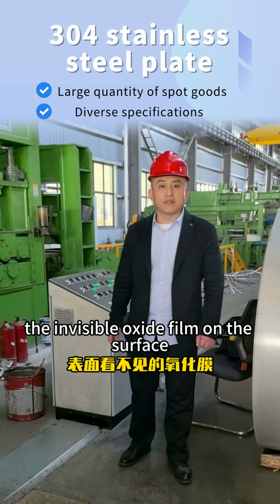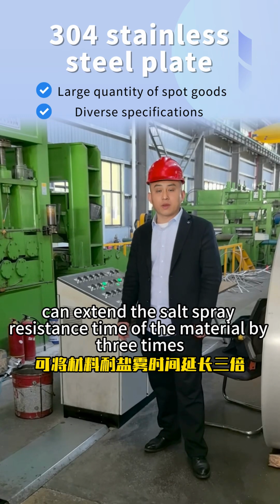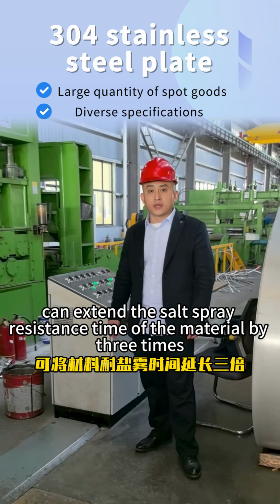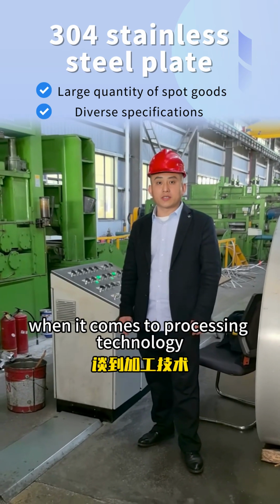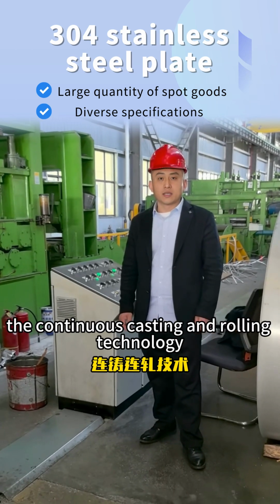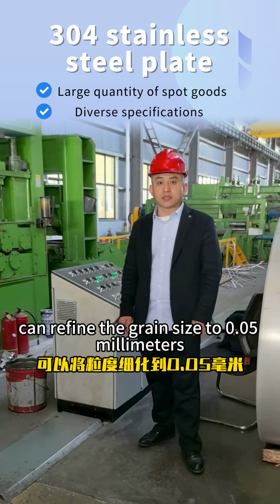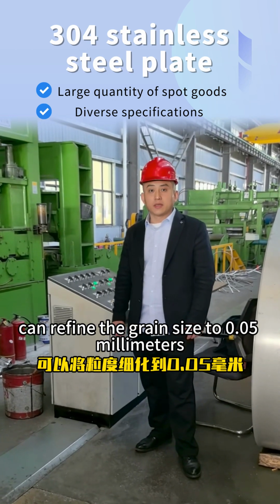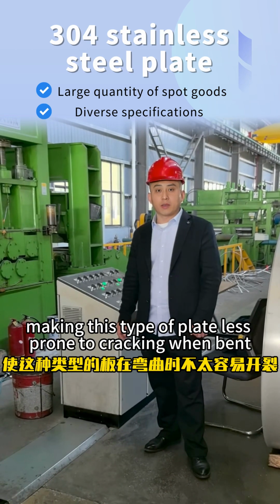The invisible oxide film on the surface can extend the salt spray resistance time of the material by 3 times. When it comes to processing technology, the continuous casting and rolling technology of Baosteel can refine the grain size to 0.05 millimeters, making this type of plate less prone to cracking when bent.